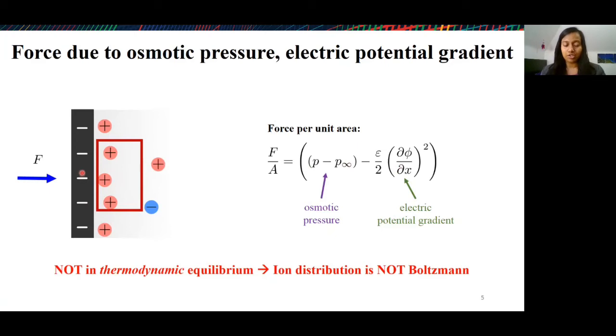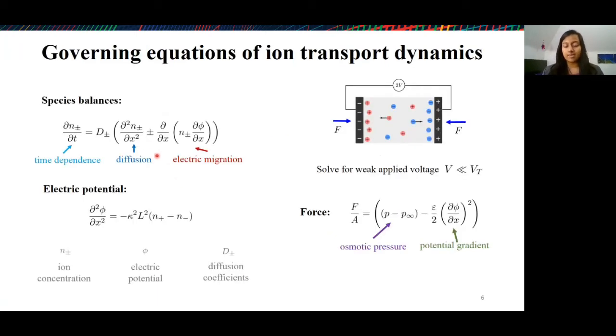So to figure out what the ion distribution looks like, we go to our ion transport model, which is basically the Poisson-Nernst-Planck equations with our species balances and electric potential balance. Here, the species balances are conservation equations for the ion concentrations N plus and N minus. On the left-hand side, we have a time-dependent term, which is how these ion concentrations vary with time. And these are balanced by the fluxes. Here, D plus and D minus are the diffusion coefficients of the ions. The first flux comes from diffusion, which is basically due to a concentration gradient. And then the second contribution to the flux is an electric migration flux, which is because of the charge nature of these species, they move under an electric potential gradient.